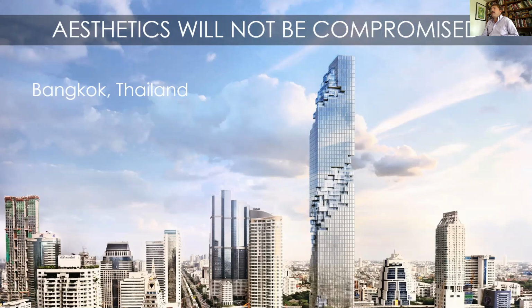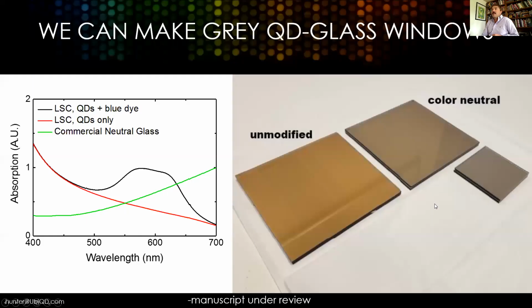Having this sort of pattern on the glass is probably not ideal for occupancy maximization, but it just goes to show that aesthetics really is king when it comes to buildings. And like I mentioned, color is a big part of that. One of the things we've been working hard on in recent years was how to balance out the color. If you just take our near-infrared quantum dots, they perform very well, but the glass, depending on the lighting and what's behind it, will appear somewhat brown.